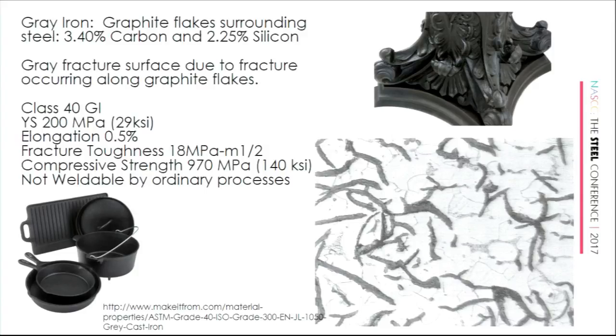So that's graphitization. And you can see that a class 40 gray iron, 40 used to be 40 KSI, you have a yield strength minimum of about 29 KSI. And because of this graphite continuity, you have almost no ductility. So in tension, it's not a very good material. But in compression, you've got plenty of properties.